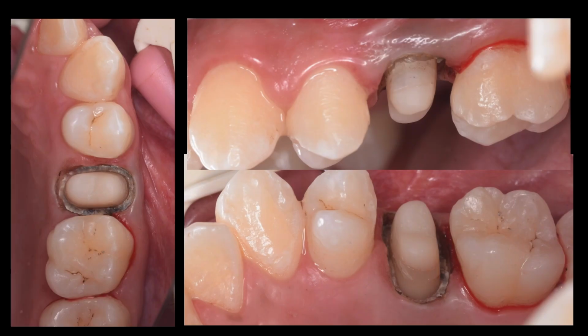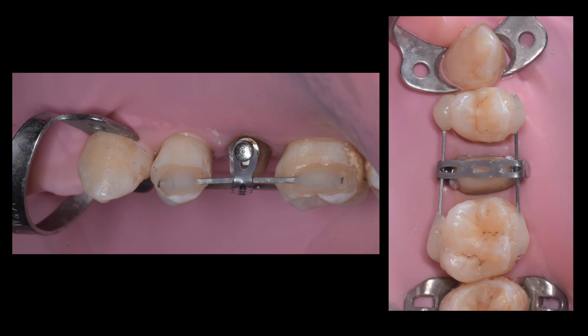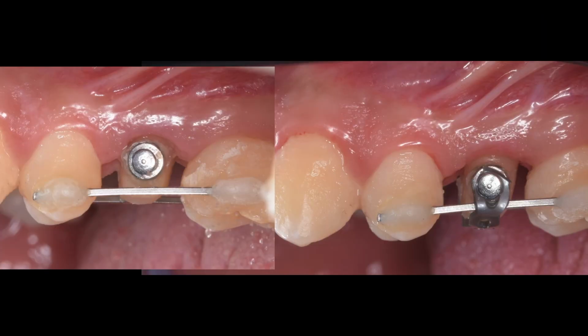But of course, we need more ferrule for the final restoration. So we make a vertical preparation without a finish line. Then we apply traction force, also extrusion of our restoration. We make the extrusion from the post and core, the hybrid ceramic 3D printed one. Okay, you can imagine we extrude from this 3D printed hybrid ceramic restoration. After only 1 week, sometimes a maximum of 2 weeks, you can see the extrusion of our premolar.